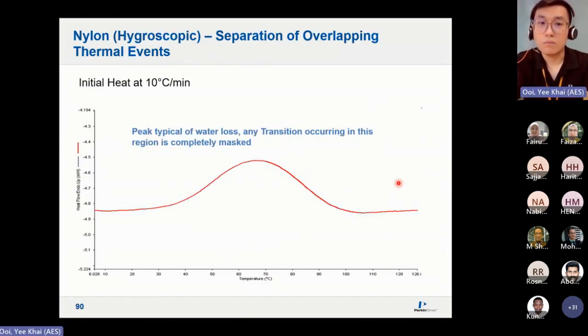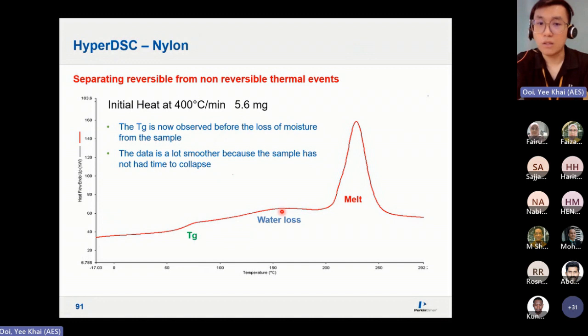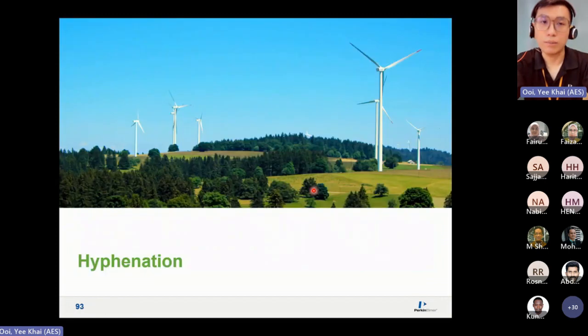Another one is if you heat up at 10 degrees C per minute, for example, nylon is highly hygroscopic, meaning it's going to absorb a lot of moisture. When you heat up slowly, all you get is one big hump like this. This is an indication of water losses or moisture losses, so nothing else is being observed. Using a very fast heating rate, we can actually split this, meaning the water losses is going to be pushed to a higher temperature. Now we can see Tg and we can see melt, because melt is definitely going to be at a higher temperature. So you see your Tg, your moisture, and your melting peak, which is not observable if you're using a conventional heating rate like 10 degrees C per minute. So these are the standards.